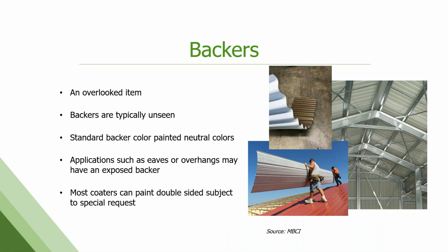Backers. The backer coat on the underneath of the strip doesn't get a lot of love, but it's quite important. It's kind of out of sight, out of mind in most installations, and overlooked. Usually a neutral color, an off-white or a light gray. That said, I should mention we can coat full color coats on both sides of the strip at the same time if that's desired. We put this backer coat on for corrosion protection and for any overhangs or eaves where you might see it, so you get a nice uniform appearance on that back side.